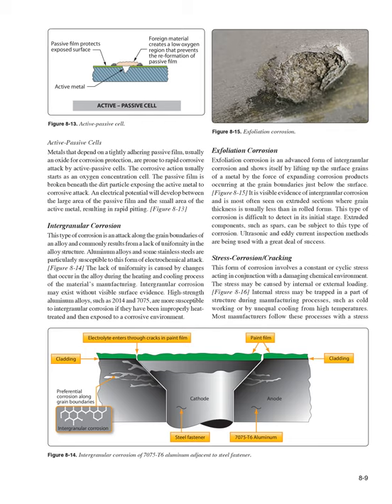Exfoliation corrosion. Exfoliation corrosion is an advanced form of intergranular corrosion and shows itself by lifting up the surface grains of a metal by the force of expanding corrosion products occurring at the grain boundaries just below the surface. Figure 8.15, it is visible evidence of intergranular corrosion and is most often seen on extruded sections where grain thickness is usually less than in rolled forms. This type of corrosion is difficult to detect in its initial stage. Extruded components, such as spars, can be subject to this type of corrosion. Ultrasonic and eddy current inspection methods are being used with a great deal of success.